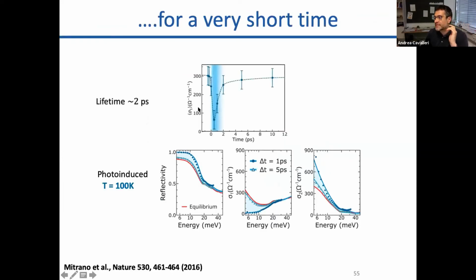What we've done more recently is to try to address, it's of course very nice that we are creating these superconducting-like features in the driven material, but the effect lives really for a very, very short time. And so it opens all sorts of problems, aside from the fact that it also makes it not particularly useful to have a superconducting-like state that disappears immediately when I'm done pumping the pulse. So here I'm plotting the size of the gap or the spectral weight inside here that goes from a finite number to 0 back to a finite number in about 1 picosecond.